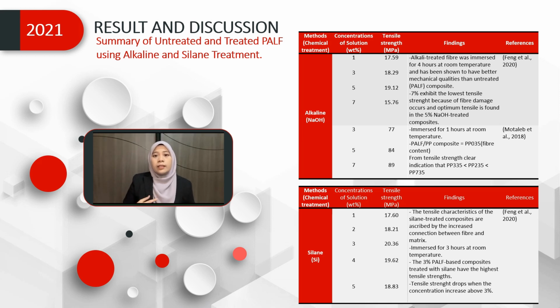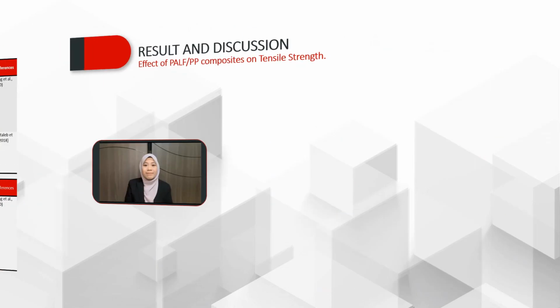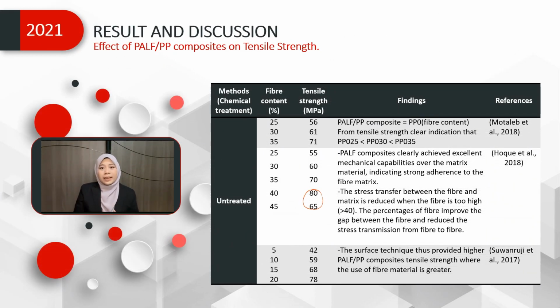However, concentrations above 5% of NaOH and 3% of silane solution caused the tensile strength to decrease. Next, based on the various studies analyzed, PALF was used to reinforce PP composites. Fiber loading also plays a significant role in determining the tensile properties. It is shown that reinforcement of treated PALF with PP has improved the tensile properties significantly. Fiber loading exceeding 40% would cause the tensile strength to decrease.